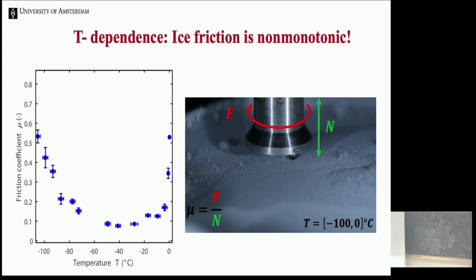Yeah, so friction is only low at roughly ice skating temperatures. But then when you go to very low temperature, it actually is larger than the friction of wood on wood, which was 1/4 as reported by Da Vinci. And then if you come close to melting, the friction goes up again. So this is non-monotonic, and this is what we need to understand, to try and understand in any case.